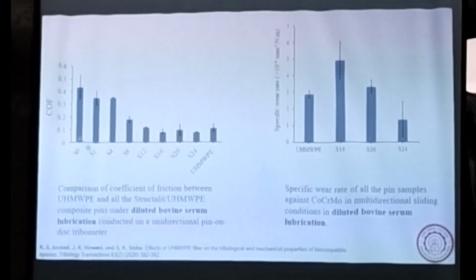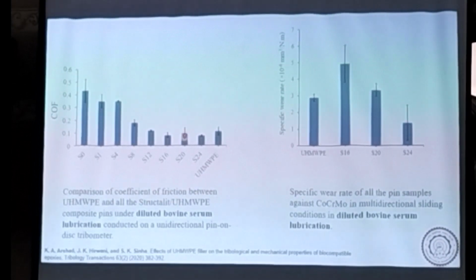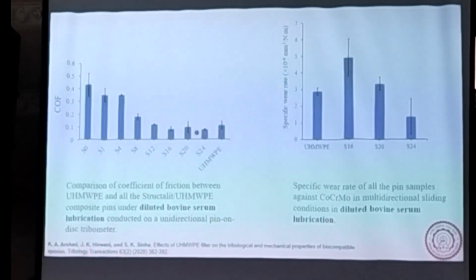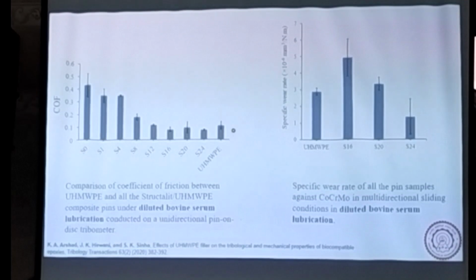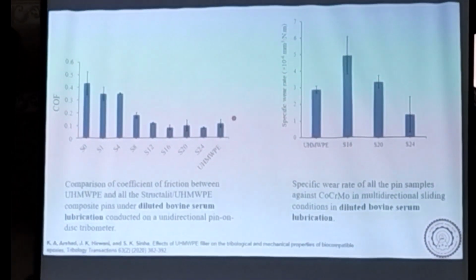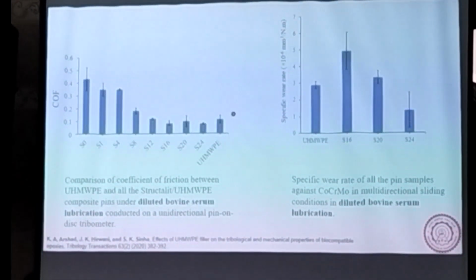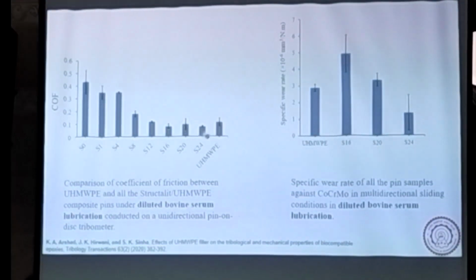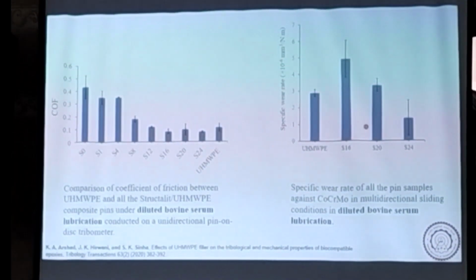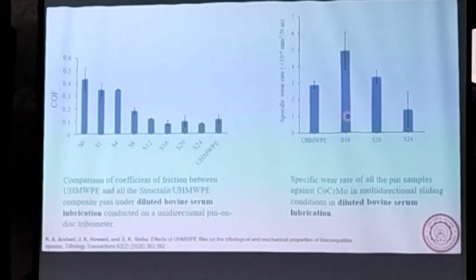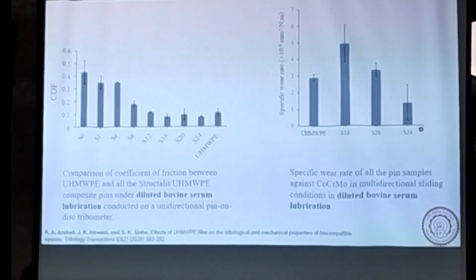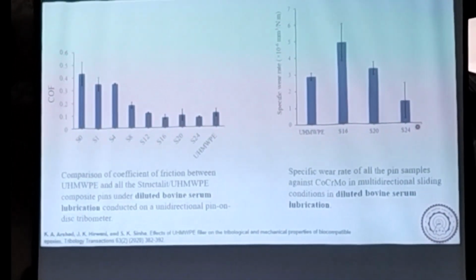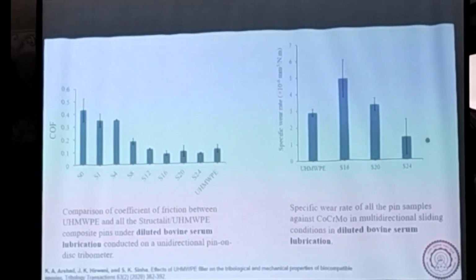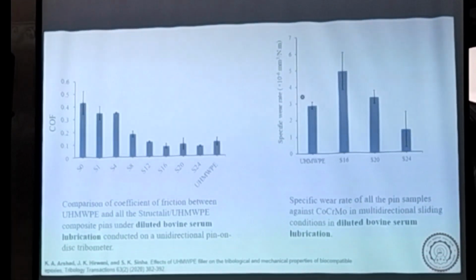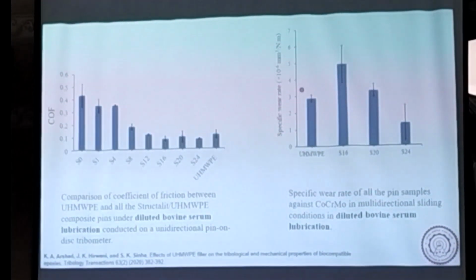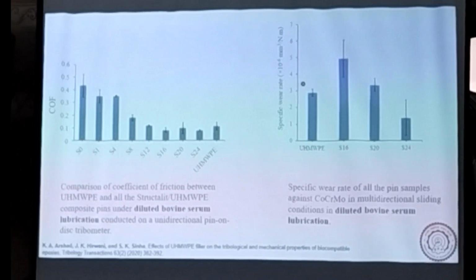So we find that Structalit with 24% UHMWPE gives a very low coefficient of friction, and here we have compared with pure UHMWPE, which is the material we are trying to replace, and it is even better than UHMWPE. And in terms of specific wear rate, we also find that 24% UHMWPE particle in Structalit gives better properties compared to pure UHMWPE. So here we see that there is some scope for a new material.